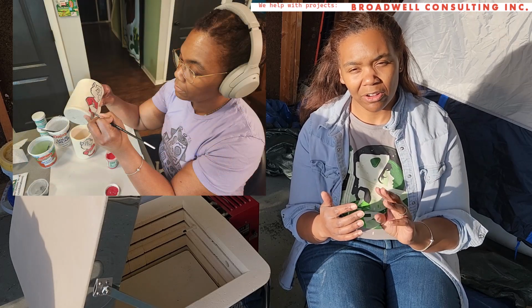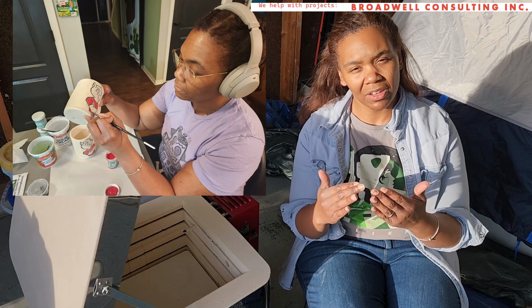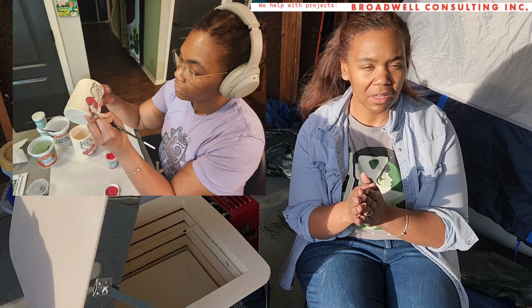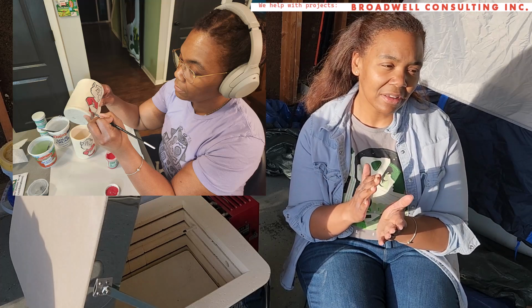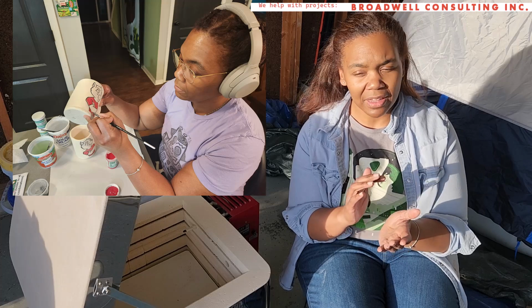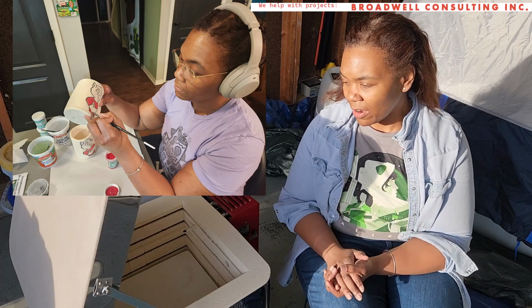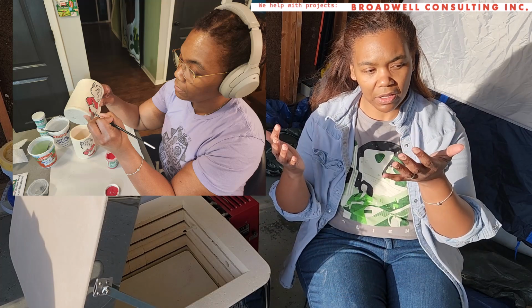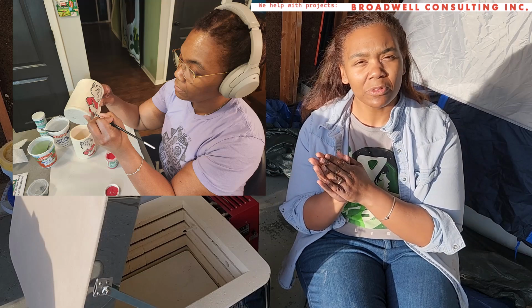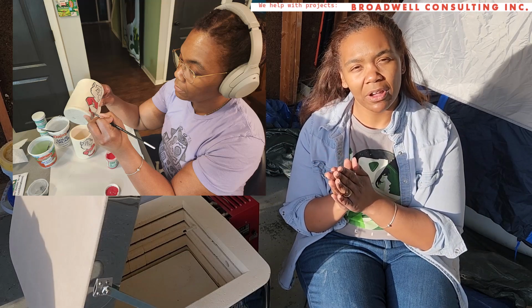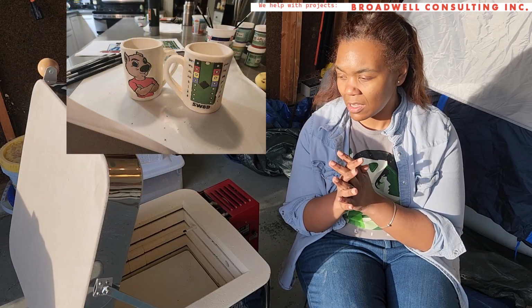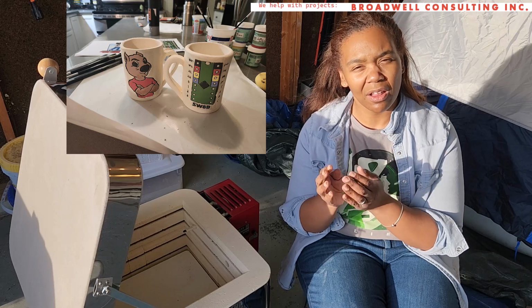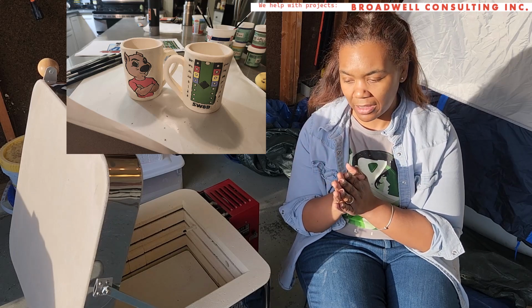I do 3 layers. You have to add underglaze in thin layers. You need multiple layers. The different colors of underglaze react differently at high temperatures. I fire at cone 6. The higher temperature you fire at, the more problems you tend to have with very vibrant colors like pinks, reds, purples, that sort of thing. They can lose their color and kind of go brown when they're fired at very high temperatures.